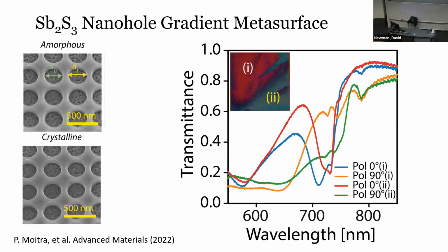One nanostructure engineering solution for the growth and nucleation problem is not to create isolated structures, but to create nanohole arrays, which also show dielectric resonances. Now, if the material nucleates from this point here, the crystal can still grow across the whole structure, because everything's connected.